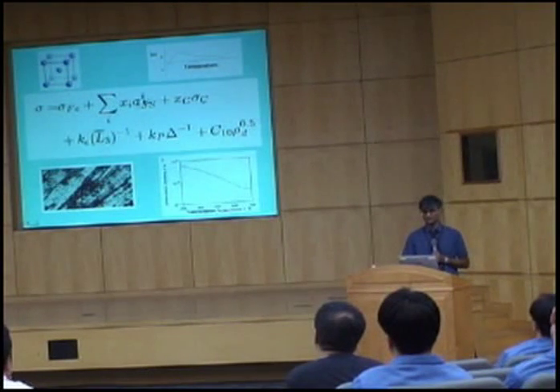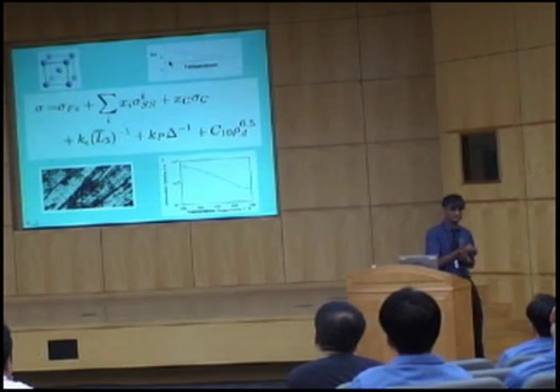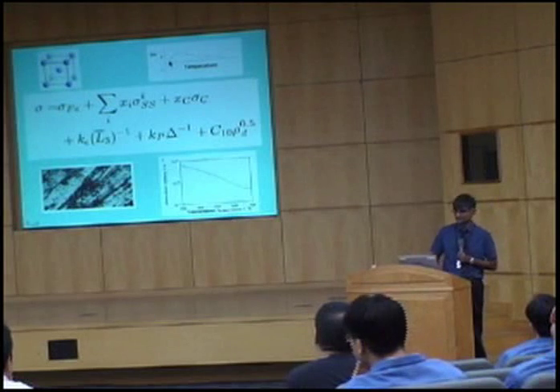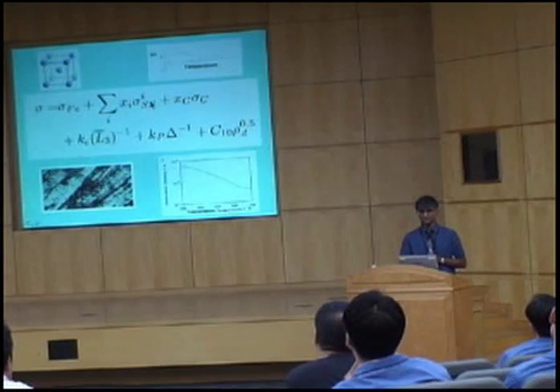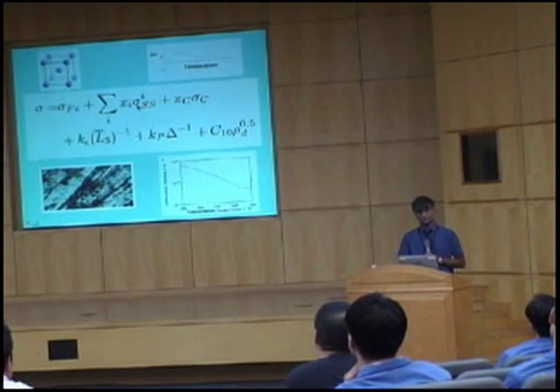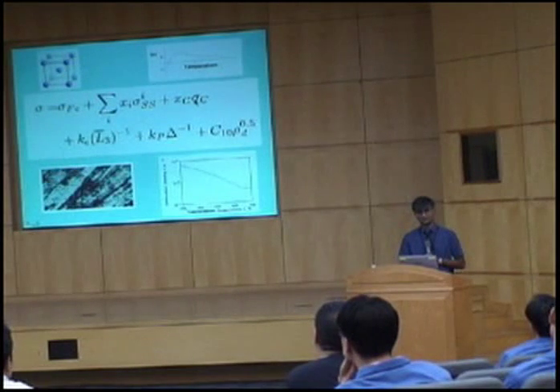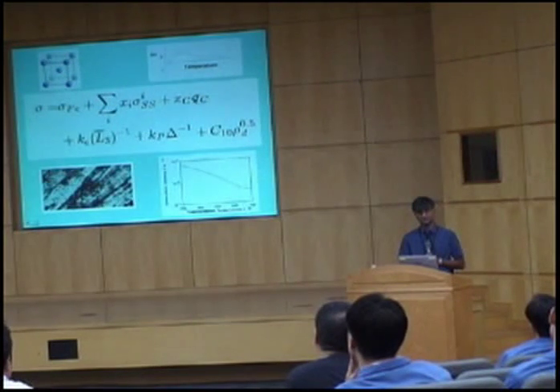We then have solid solution strengthening components, and those components vary with temperature. So the amount of solid solution strengthening that you get depends on temperature. And the behavior of substitutional solutes is different from that of carbon. So carbon has a different strengthening effect than substitutional solutes, and we will see why.